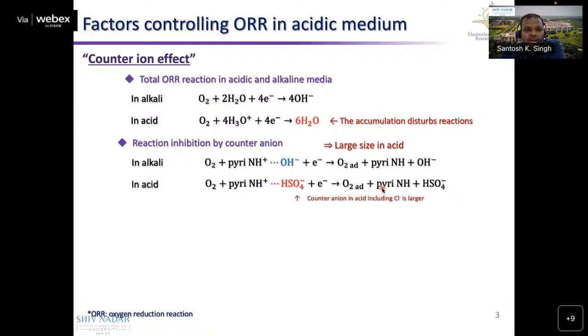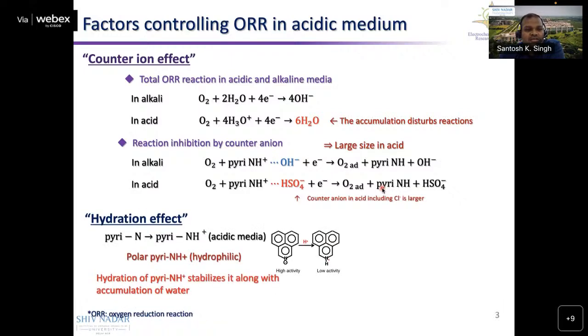So this is one problem which controls the activity, and it is also well known that in the acidic medium, this pyridinic nitrogen converts to the pyridinium ion in the presence of H plus ion, and this pyridinium ion is highly hydrated in the presence of water. That also restricts the higher ORR activity of these nitrogen doped carbon materials. So how can we improve the activity?